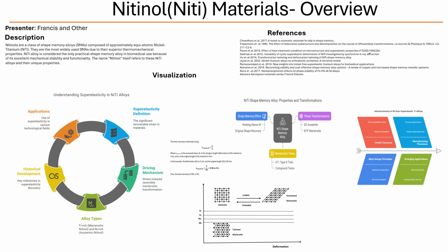Well, those diagrams show us that the amount of unrecoverable strain tends to increase exponentially as you increase both the stress and the temperature during those transformations. And what's even more interesting is that the reverse transformation, when martensite changes back to austenite upon heating, it can actually create as much or even more permanent strain than the initial forward transformation.